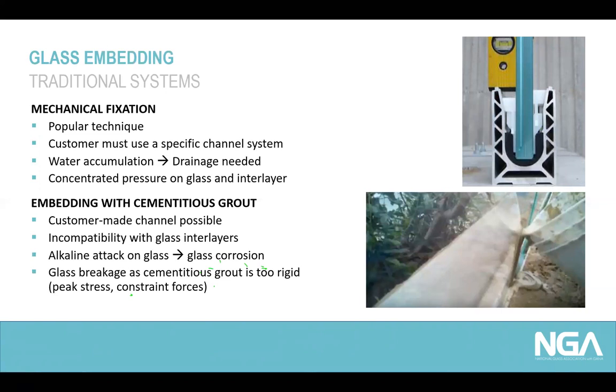There's also a traditional embedding system, which is based on cementitious grout. That embedding system already enables the combination of customized U-channels with every kind of glass unit. Tolerance can be accommodated by the liquid applied grout. But here we have to take care that compatibility between the used grouting material and the glass interlayer is given and proven. Alkaline attack on the glass can cause glass corrosion, and cementitious grouts also tend to be very rigid after curing. That can increase the risk of glass breakage due to peak stress and constraint forces.